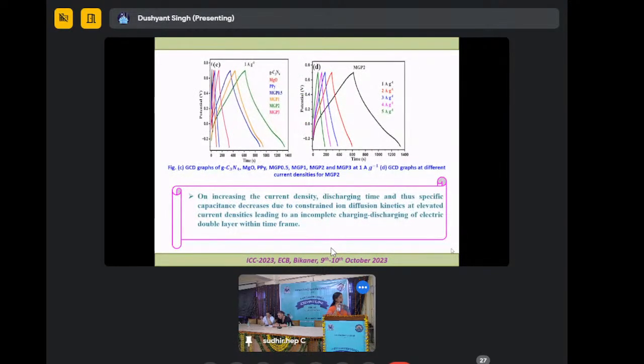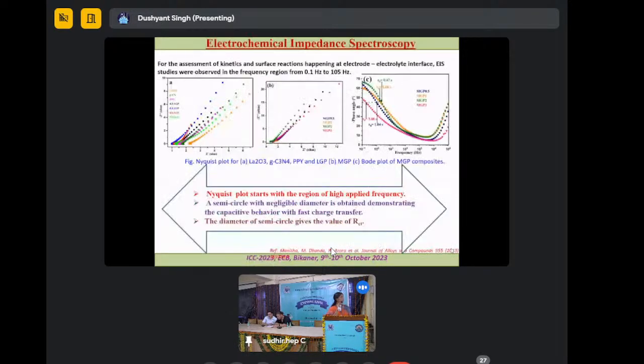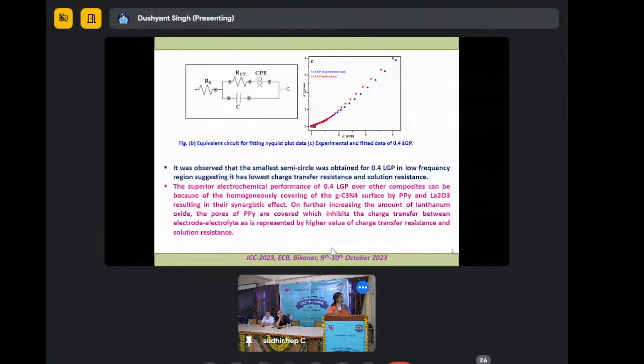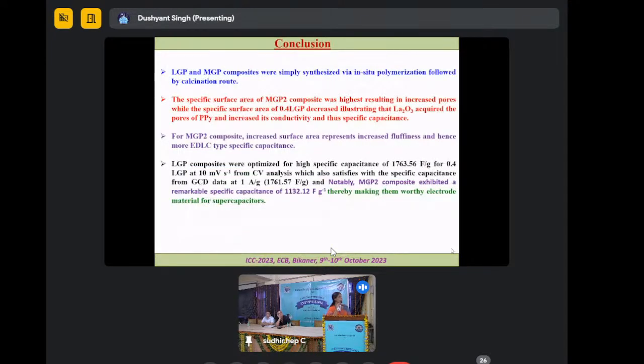and for the MgP, and this also shows that on increasing the current density, discharging time, and thus specific capacitance decrease due to the constraint of ion diffusion and incomplete charging and discharging of the electric double layer within the time frame. So this is the EIS spectroscopy, which also indicates that the diameter of the semicircle gives a value of RCT. Means we can find out that these materials are suitable for supercapacitor electrodes, and these are the conclusions.